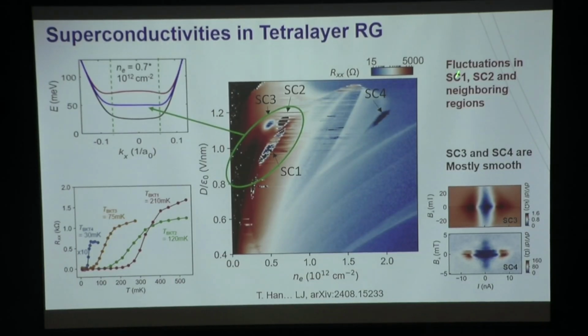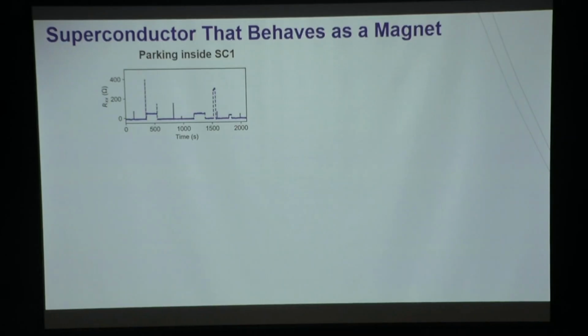Well, SC1 and SC2 look very fluctuating, and we decided to look into what they are. The first thought that came to mind is, okay, you have a lot of fluctuation. Maybe that's because you're scanning the gate voltage, you are triggering something by changing the voltage on your source meter, and maybe that caused the sample to be somewhat unstable and give you fluctuations. So the first thing we did is to park inside the SC1 region.